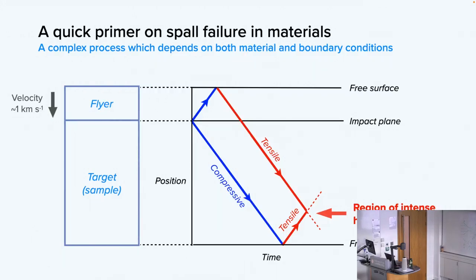And what those tensile stresses can do to the material is cause cavitation, so nucleation of voids, which then grow. And if those voids link up, they cause the kind of spall failure that you saw in the previous slide. I'll just point out that in this particular diagram, notice that this dimension, the thickness of the flyer, is exactly equal to the distance from the spall plane, the region where the hydrostatic stress is a maximum, from that free surface.